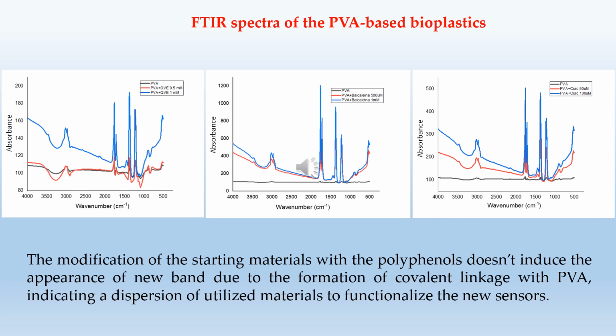In particular, they can be attributed to the greater vibration energy of the carbonyl group present in the identified flavonoids and to the water molecules bound. There are some changes also in the bands at about 1100 cm-1 influencing the sequence with crystalline and amorphous structures that are directly related to the modification of the PVA.